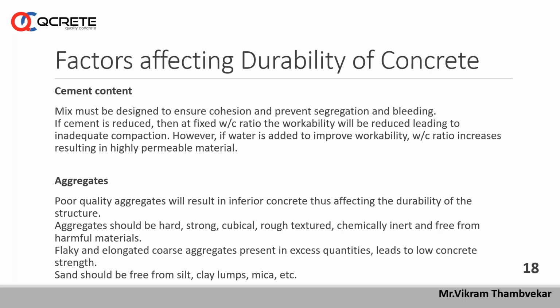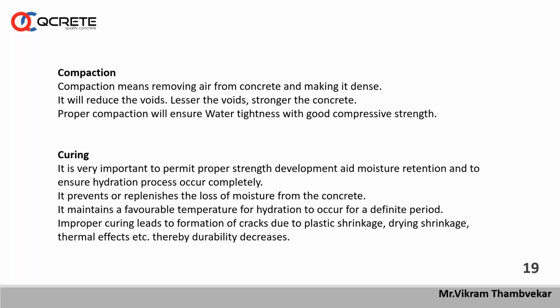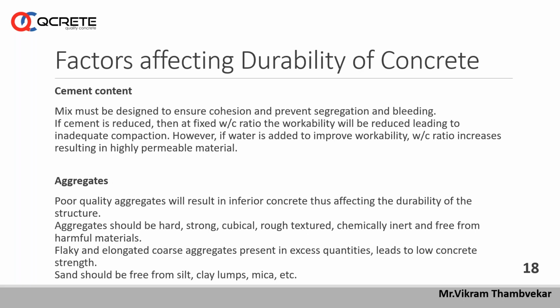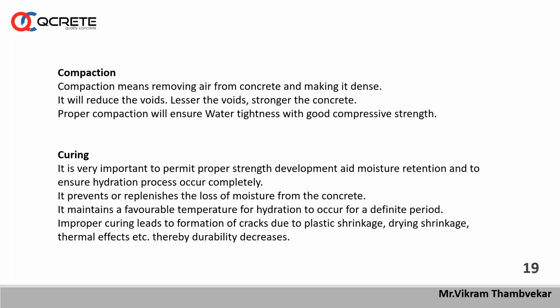The factors affecting durability of concrete depend on various parameters. That is, of course, cement content, then other binder content, quality of aggregate, quality of water, and use of admixture, type of admixture, etc. See, when RMC supplies fresh concrete of very good quality at site, if proper precaution is not taken to discharge the concrete properly, make a good compaction, and give very good curing, etc., durability is affected, as well as strength is also affected. So we have to take care of all these practical uses of concrete at site, even though very good quality of fresh concrete is delivered at site.